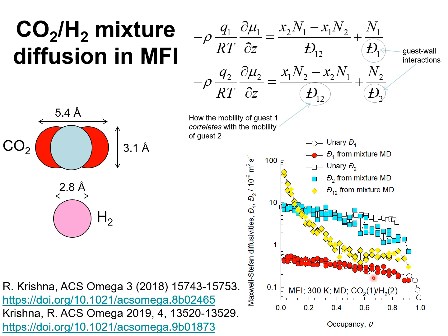The first thing to observe is that the Maxwell-Stefan diffusivity of either component in the mixture is practically the same as the Maxwell-Stefan diffusivity for unary diffusion.